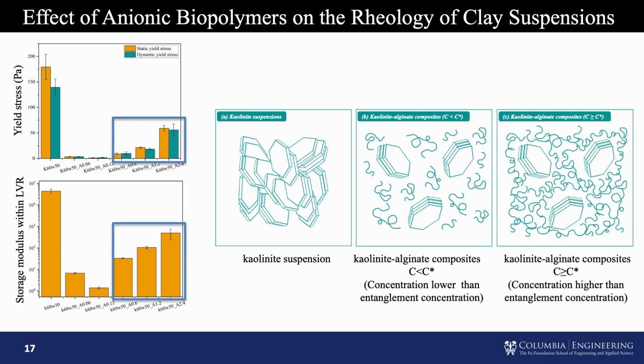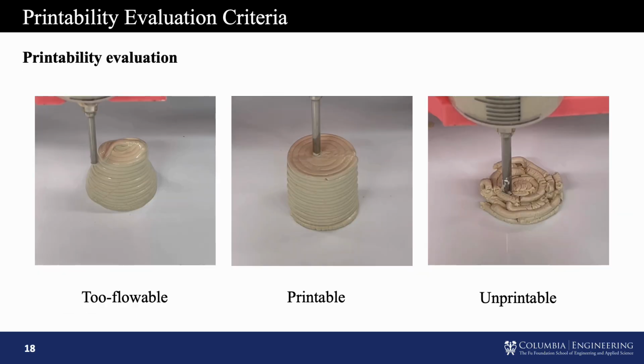But if you keep increasing the polymer concentration, eventually the polymers start to overlap with each other to create a three-dimensional polymer network, which eventually increases the yield stress and storage modulus. Now we know how these anionic polymers affect the suspension rheology, and let's see how this rheology translates to the printability of the material. The goal of studying the rheology of clay-based systems is that it can help us understand the printing process.